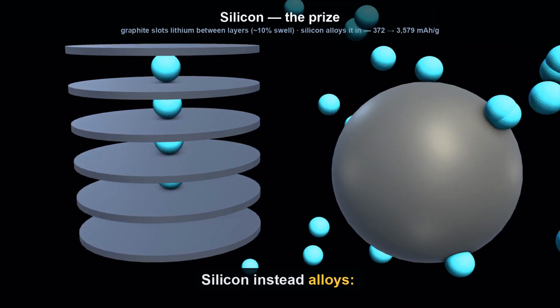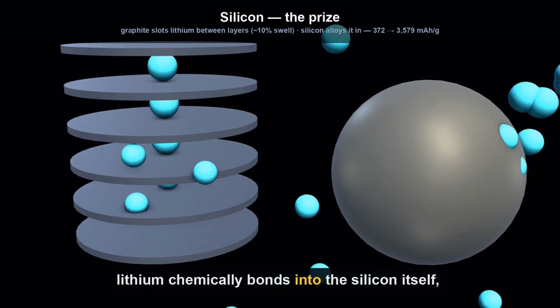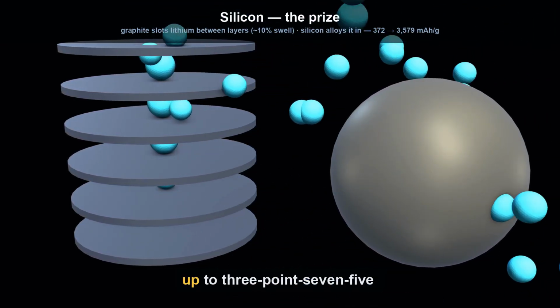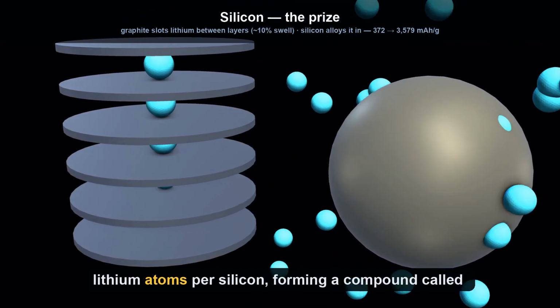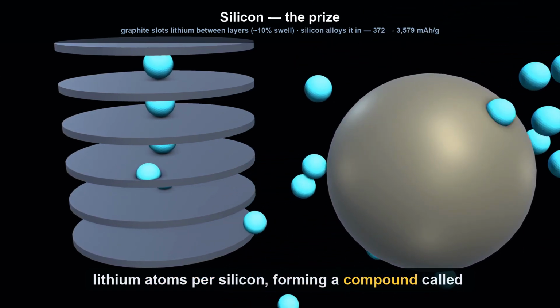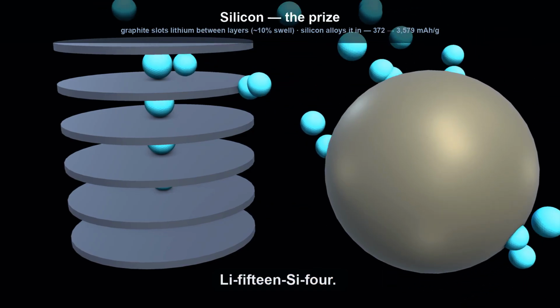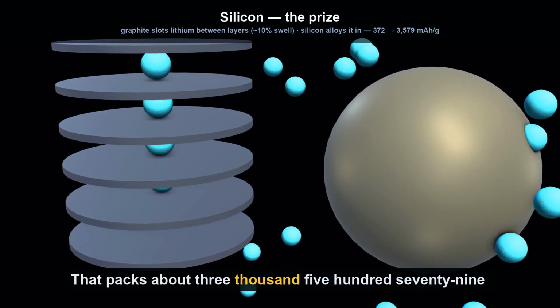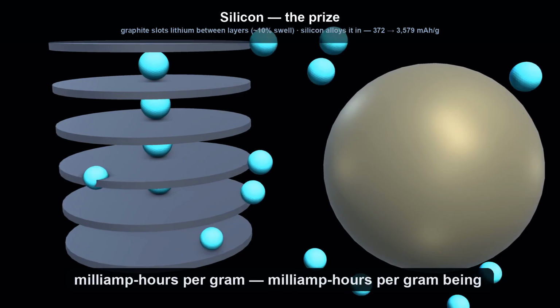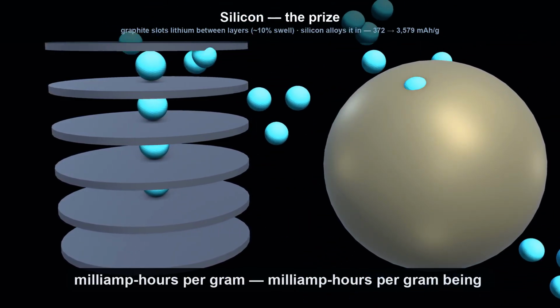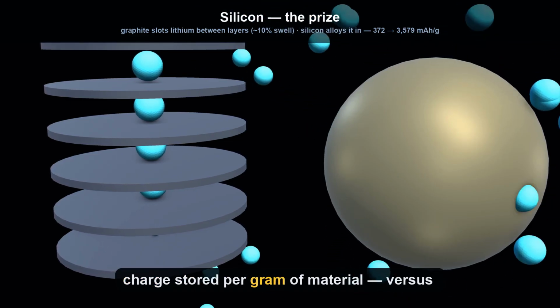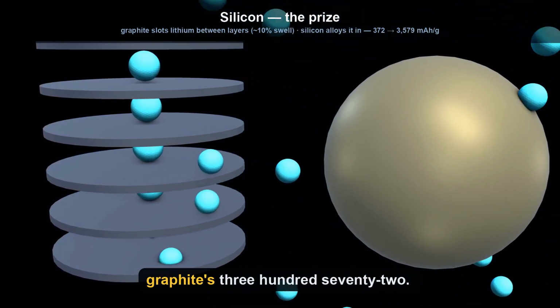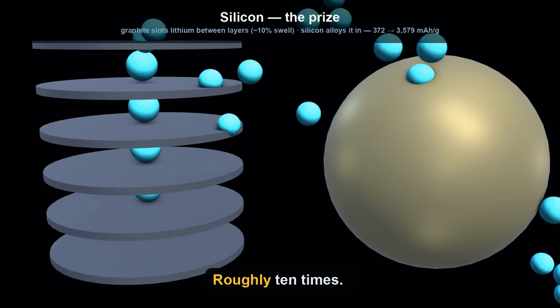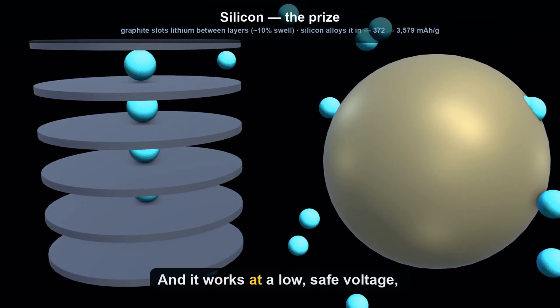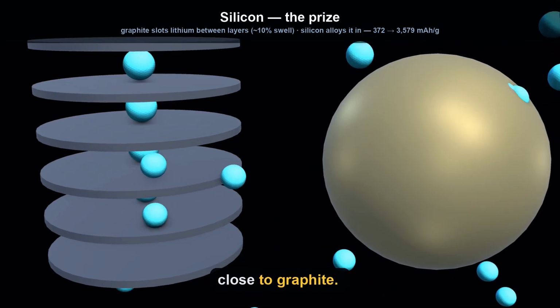Silicon instead alloys. Lithium chemically bonds into the silicon itself, up to 3.75 lithium atoms per silicon, forming a compound called Li15Si4. That packs about 3,579 milliamp hours per gram, milliamp hours per gram being charge stored per gram of material, versus graphite's 372, roughly 10 times. And it works at a low, safe voltage, close to graphite.